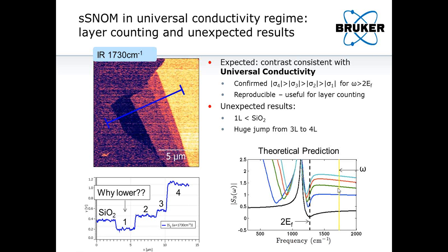That is not what we observed, however. And this theoretical prediction was made using the random phase approximation for graphene. So there may be some additional elements that need to be introduced into this model in order to account for these experimental results that we're getting.